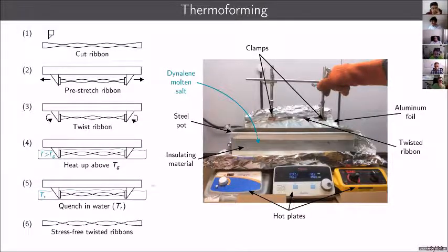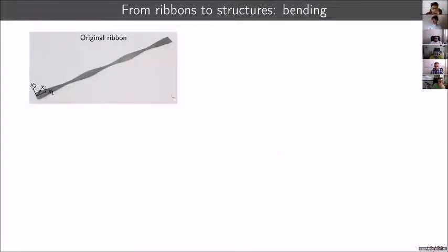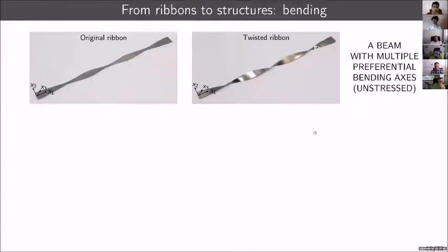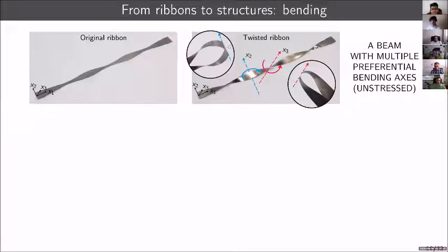So this is our fabrication apparatus. It's quite rustic, and yet we have these hot plates here at the bottom and our dynalene salt bath over here. So this is an original ribbon. And upon twisting it and thermoforming it, you obtain a twisted one, for example, like the one that I have here in my hands. And it's quite nice. So it's virtually stress-free. And what we obtain is basically what we wanted in the beginning, which is a beam, a structural element of some sort, with multiple preferential bending axes, okay? Because all these thin necks are parallel to each other and can bend about the X3 plane, as you can see over here. While the wide faces are all parallel to each other and can bend about X2.